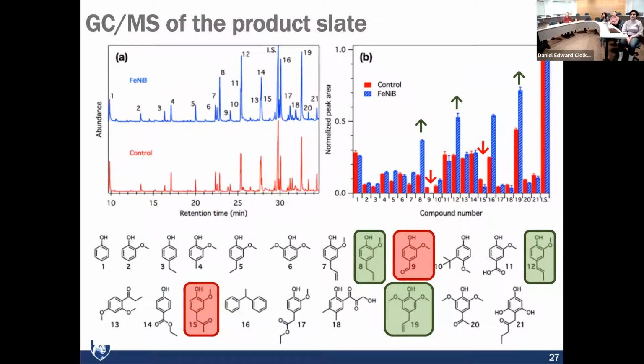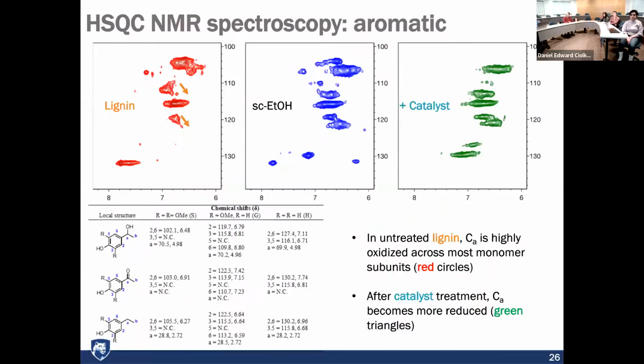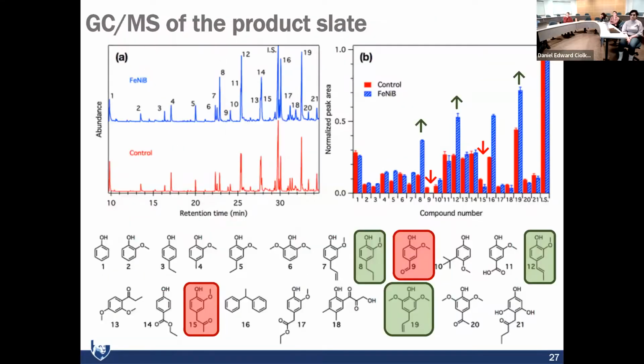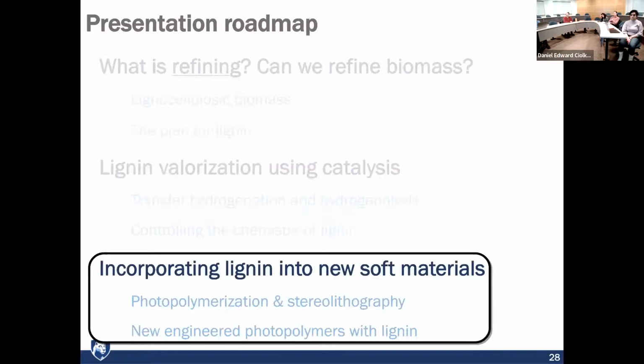And then we can look at the product slate by GCMS. So now we're actually identifying individual compounds that come out in our reaction. And what we see is an increase in things that look like, say, 8 or 12 or 19, where these green arrows are. Those things increase because there's no hydroxyl group at that alpha carbon. That's that one right there. And a decrease in things that look like, for example, number 9 and number 15, where this is an aldehyde, and here we have a ketone at the beta carbon. So things with oxygen in them go down and things without oxygen go up. But again, we'd like to get that intermediate one where we have that hydroxyl group. We're sort of over reducing our material.